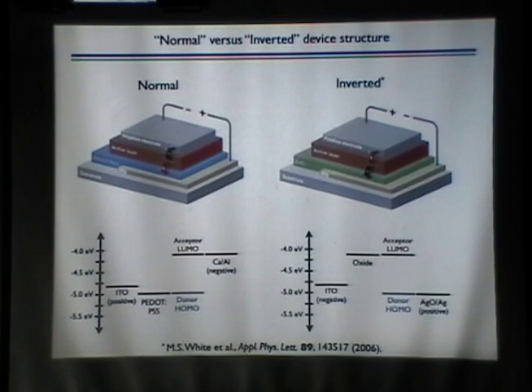Now what we do is deposit silver, and normally silver, if you look in the handbook of chemistry and physics, has a work function close to that of aluminum. But in reality what happens is it oxidizes a little bit, you get silver oxide, and this work function is now further from vacuum, close to the donor HOMO level. So now we flip the device around. The advantage is now we have a chemically stable device. Since calcium oxidizes very quickly, the other device is not particularly stable, and one would need to do more effort to encapsulate it from oxygen so that it doesn't oxidize.